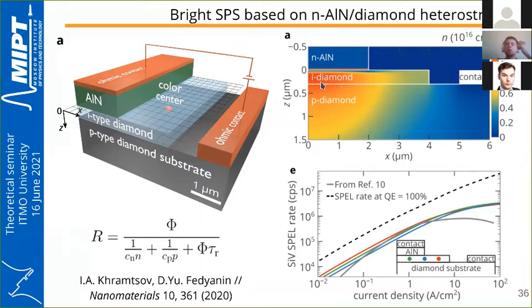That should result in a high SPEL rate for the color center located here. And yes, if we put a silicon-vacancy center here in this I-type diamond and look at the dependence of its SPEL rate on the current density, we can see that it can be as bright as 3 million photons per second.